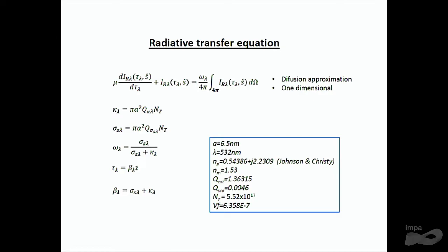These are the refractive indices, real and imaginary part, of gold. This is the refractive index of the polymer matrix. And these are the efficiencies that we calculated. As you see, the system is mainly absorptive because the scattering efficiency is very low.